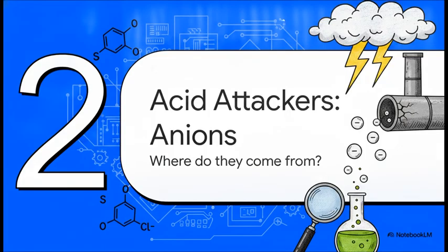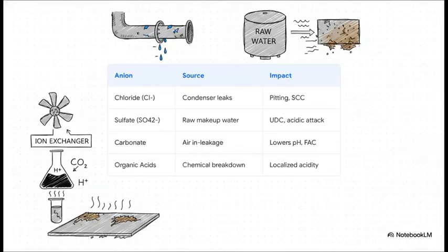Moving on to Section 2, acidic attackers, the anions. Let's see where they come from. What's really interesting here is how these anions usually sneak into the system through just common, everyday operational hiccups. Take chlorides, for instance. A simple cooling water leak in your condenser, especially if you're running seawater or brackish water, and bam, you've introduced chlorides that lead straight to severe pitting and stress corrosion cracking in your stainless steel components.